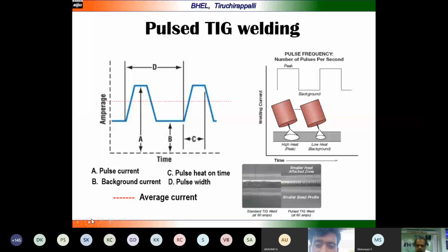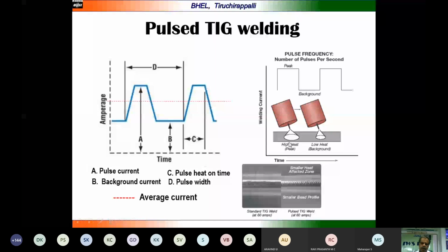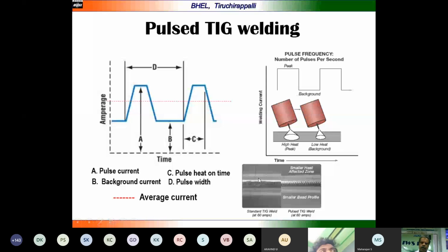Pulsed TIG welding is the first development that happened in the TIG welding process. In place of conventional TIG welding, where continuous current flows, here, as in any pulse mode, there will be a base current and a peak current, with a base current time and a peak current time. Because of that you can see the high heat input and low heat input from the background current. With the standard TIG welding and this pulsed TIG welding at the same current, you can see the difference in the bead width and the penetration. More heat density can be given, and totally lesser heat input will go into the material, so that it will avoid the heat input related defects at a later stage.